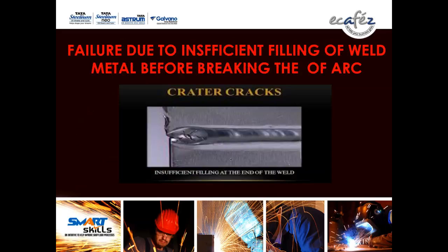Typical failure: failure due to insufficient filling of weld metal before breaking the arc. This is an example for any process. If you go for MMA, TIG, MIG, this crater crack occurs in every welding joint done by an untrained welder. This shows the reason: filling is not done, insufficient filling at the end of the weld.